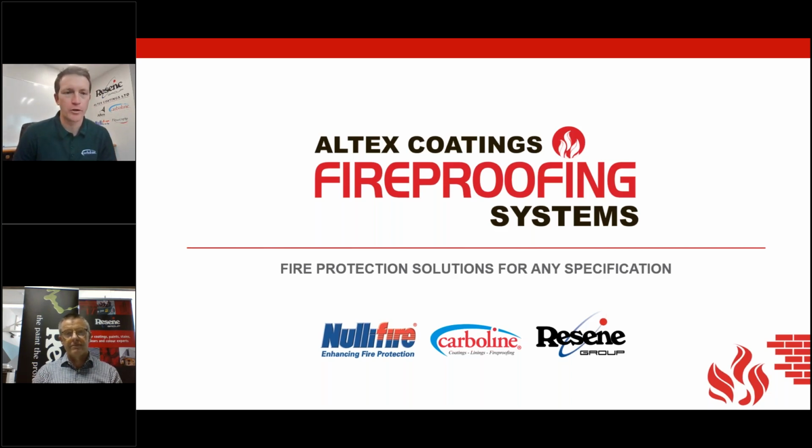You really only have to watch it if you've got 120-minute ratings in which your limitations are very close to those maximums. So within our coatings, you've got a maximum of your maximum tested plus a 10% slot factor over the top of that, just to allow for a little bit of practical overbuild in there, which is inevitable anyway, but it's still within kosher limits with regards to the testing. So yes, it is not so much a worry, really only to do with the 120 minutes that you need to be cautious of.